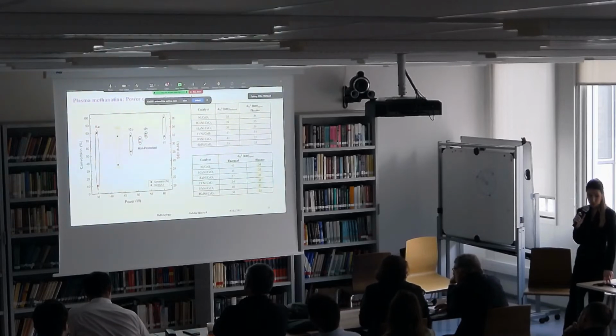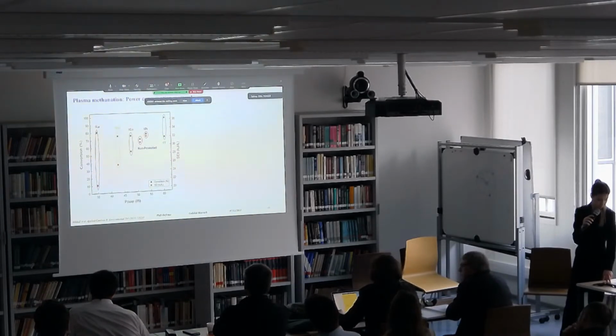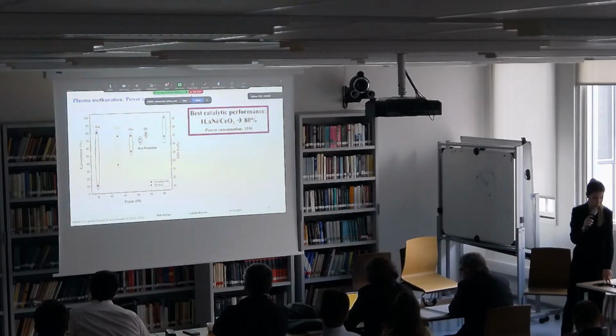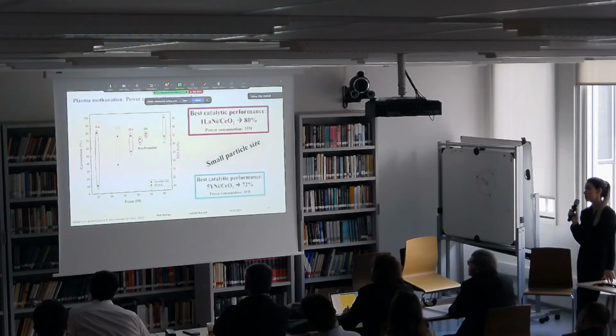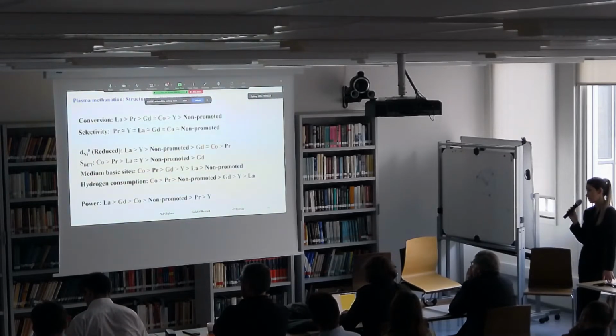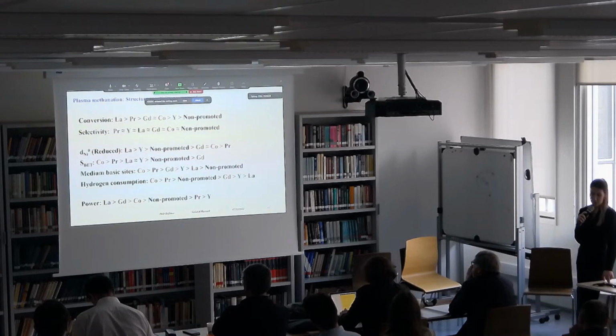Also under plasma, this series of promoters showed more resistance to sintering than under thermal conditions. So just to summarize, we already saw that the 1LA promoted sample has 80% conversion and 35 watt power consumption. Also, it has the smallest particle size, and compared to the previous catalytic performance, it showed even better performance with lower loading. Again, I gathered the different properties of the catalyst. Again, it can be seen that except for the small particle size, there is no specific trend. So definitely there is another property that plays an important role, which we'll see later.